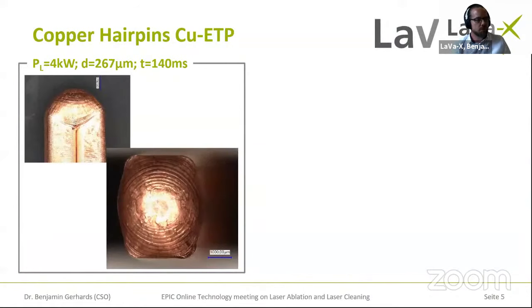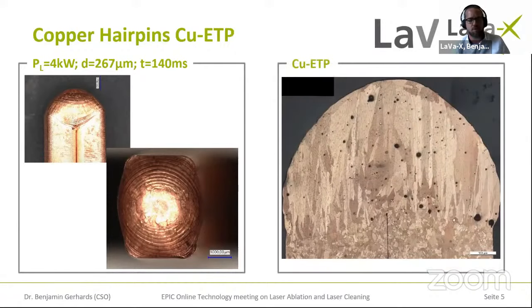We can also do the same with a multi-mode laser. And this time we used a disc laser by Trumpf. And this here is a weld that was conducted on ETP copper, which is not very common. Most of those car manufacturers use the oxygen-free grade because of the pore formation that you usually have when welding the ETP copper. But also in this case, you can see with adapted process parameters, there are very, very tiny pores that do not really reduce the connectivity significantly.